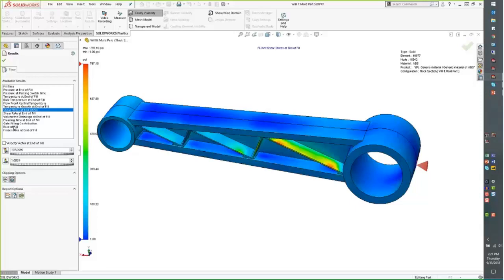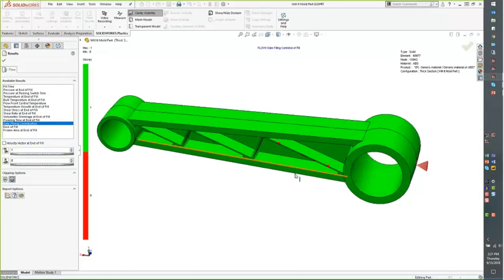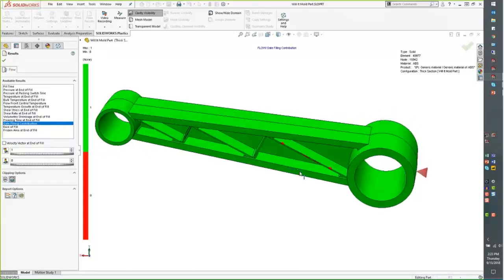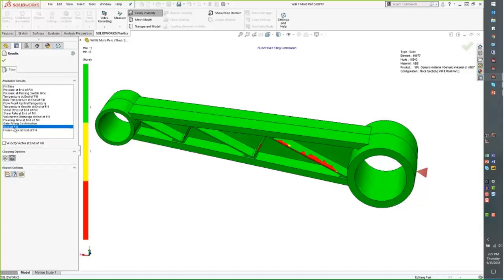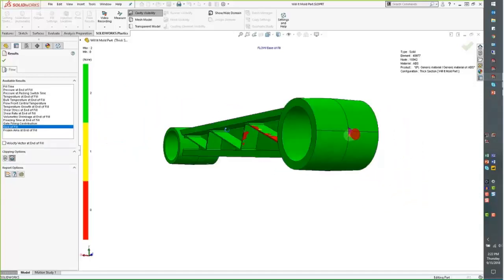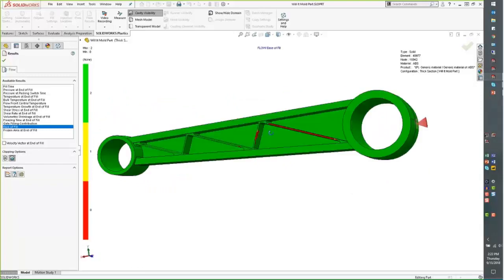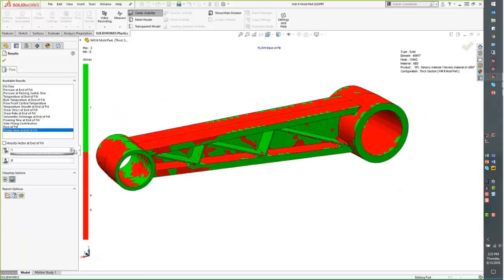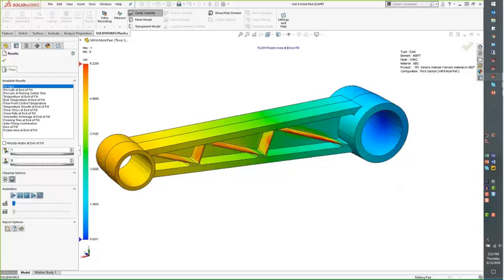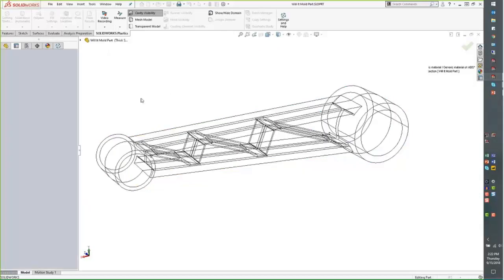One of the other things that we can see is this gate filling contribution. You can see these little red areas. Those did not fill. We had a short shot in the part. You can also see ease of fill, and this really indicates those areas that we have problems with fully filling the mold. And then another is the frozen area at end of fill. So what parts are frozen or essentially solidified, what parts are not, and we can see that we have some issues in there. So a lot of good feedback with regards to what's happening in the part, and really the big one there is that red light, yellow light, and green light indicating, hey, we have a short shot. We have some design problems with this part.